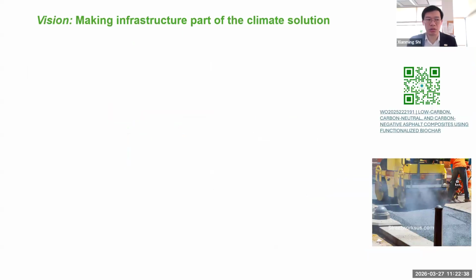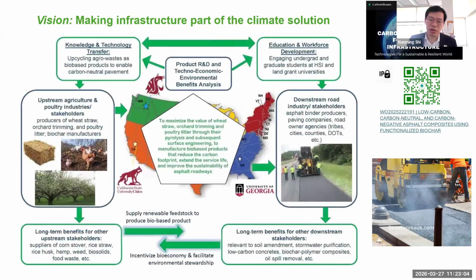So again, in addition to putting engineered biochar into cementitious composites such as concrete, mortar, grout, or paste, we also try to engineer it so that it's suitable for asphalt. As you can see here, when we pave asphalt, there's a lot of toxic fume coming out of the pavement. That's one issue. Also, asphalt pavement by itself has its own carbon footprint. We have an ongoing study, even though it's not part of today's talk, sponsored by the U.S. Department of Agriculture, trying to divert agriculture waste or farm waste towards this process to produce biochar. Then biochar would replace a part of the asphalt binder and some of the mineral fillers in the asphalt mixture and make it net zero.